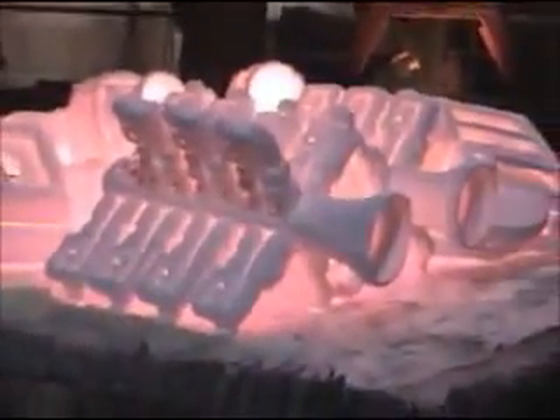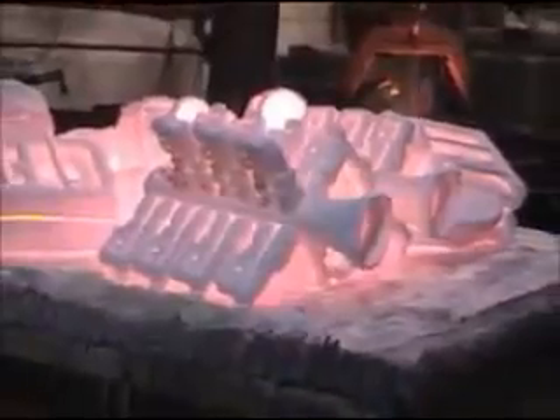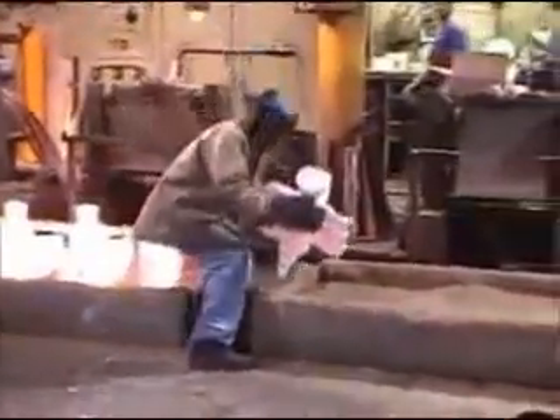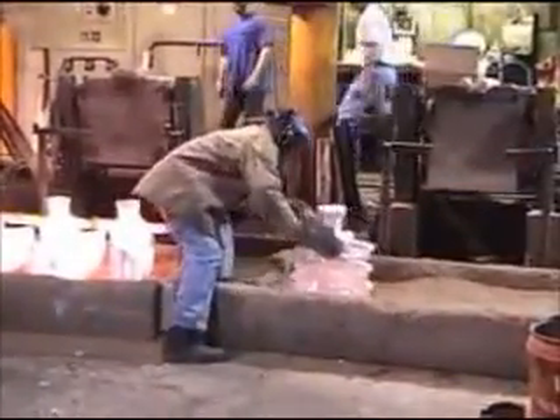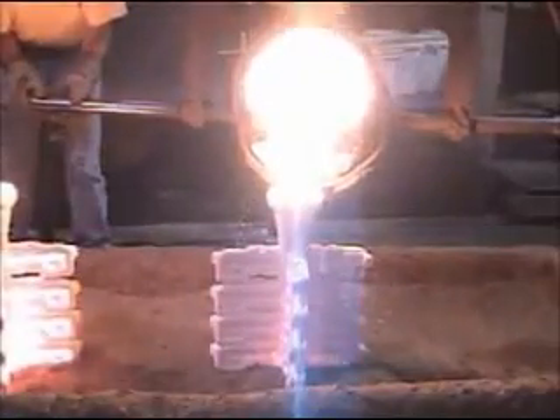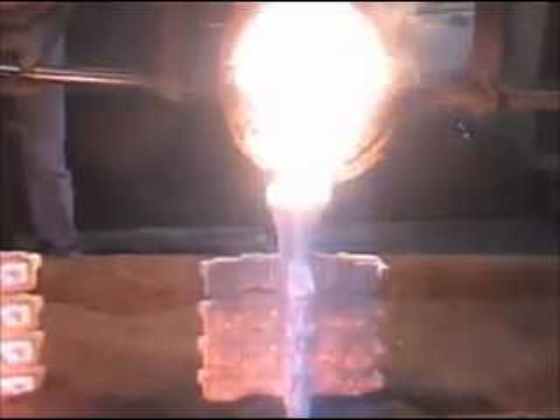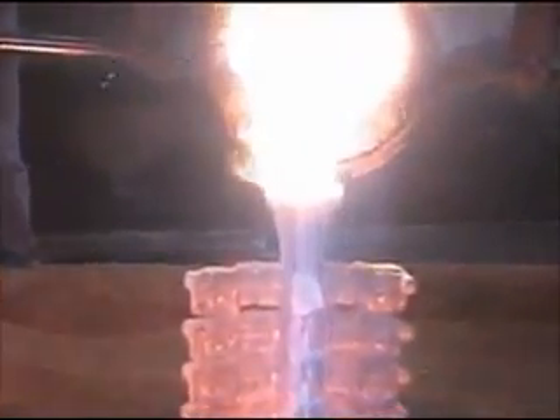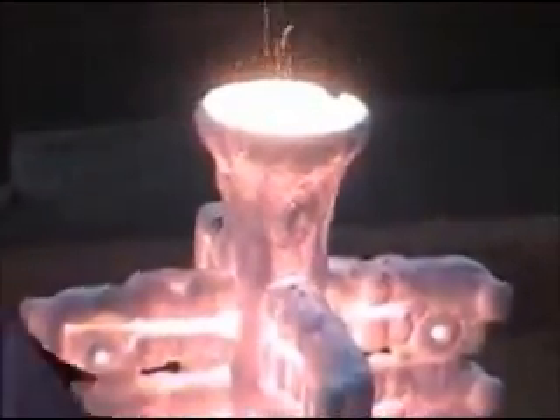The ceramic shell must be allowed to preheat for a minimum of 2 hours before it is ready to accept molten metal. The ceramic shell is then manually unloaded from the oven and carefully set in the pouring pit. Molten metal is then poured into the preheated shell at 3050 degrees Fahrenheit. This pouring process must be accomplished quickly yet precisely in order to ensure that RLM's quality standards are met. The shell is then allowed to cool in the pouring pit until it can be safely moved.